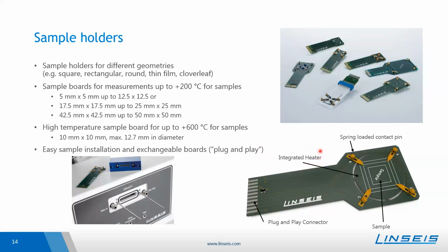What is very unique here is that we have an integrated heater on this measurement board, so that the sample will be heated from the bottom, and by that really fast heating and cooling rates can be obtained, as not the complete measurement chamber needs to be heated with an external furnace. Only the cooling is performed with the liquid nitrogen and not with the measurement board. In a more special setup, we use ceramic measurement boards so that measurements up to 600 degrees Celsius can be realized. But for the usage of the ceramic version, also the measurement electronics, so the hardware, needs to be changed a little bit.